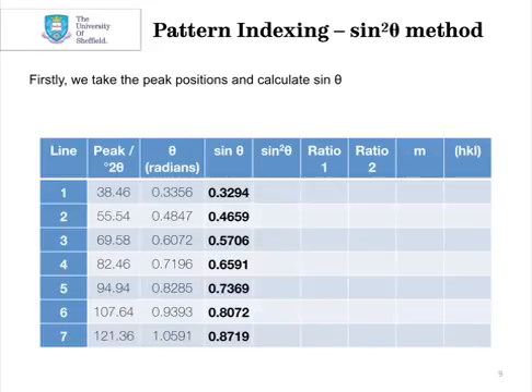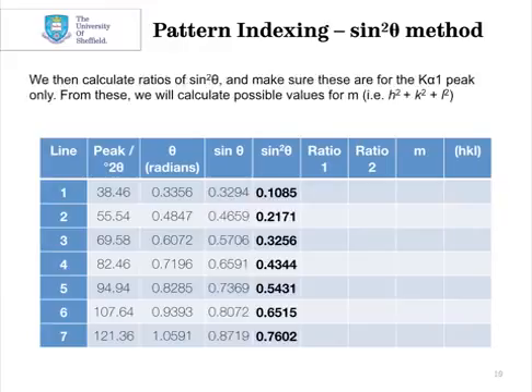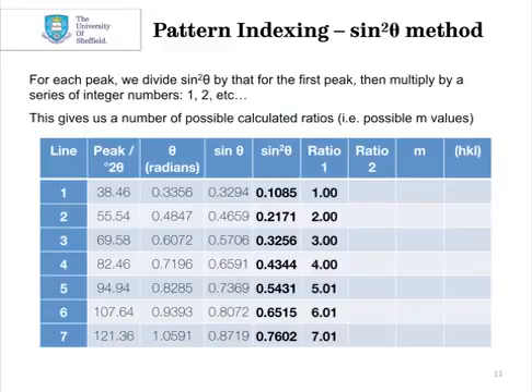So sine theta for our peak at 38.46 becomes 0.3294, and so on. We can then also square those values, so just multiply 0.3294 by itself, and that will give us a sine squared theta value of 0.1085. So that's our sine squared theta value for peak 1, and so on. We then take the ratio of all the sine squared theta values compared against the first peak. Actually, you can pick any peak, but I tend to always work from peak 1.